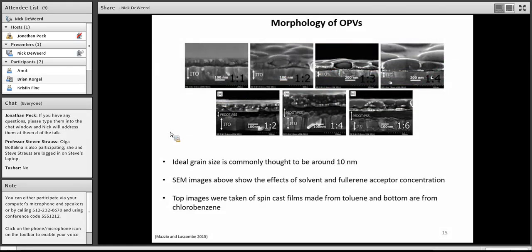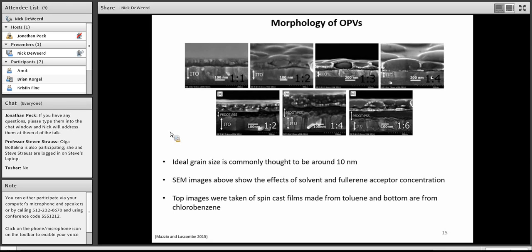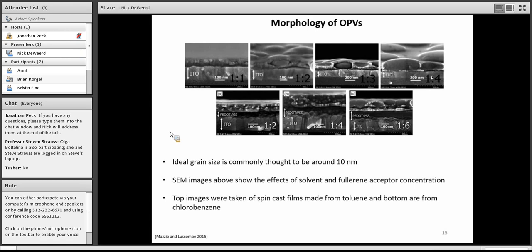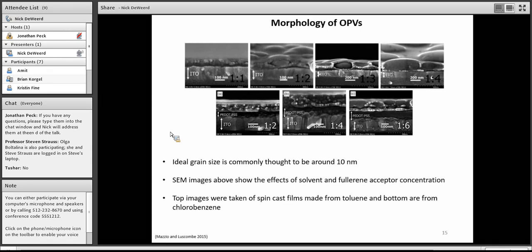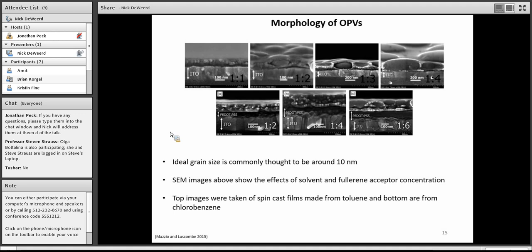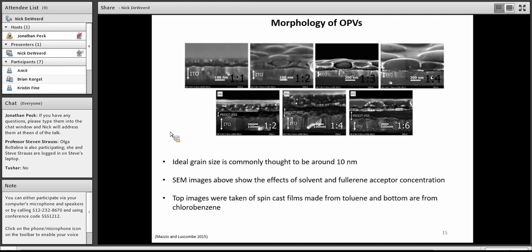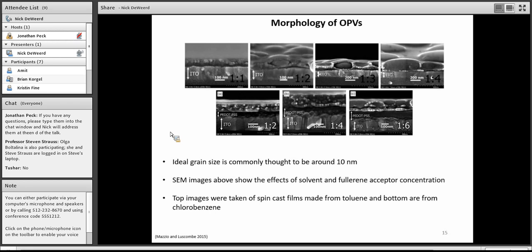That morphology keeps getting more and more complex the more layers you have to deal with. Here is a basic rundown of those morphology problems. This is just a couple of variables being changed, and you can see here how large the difference is in the morphology between different active layers, depending simply on the conditions in which those active layers were deposited. In the top row of SEM images, you can see the ratios actually correlate to the donor fullerene ratio, where the fullerene ratio is increasing, and that's true for the bottom layer as well. The top layer is a spin-coated active layer that was deposited in toluene. As you can see, as the concentration of fullerene increases, we're getting larger and larger aggregates. These aggregates are going to be much larger than the optimal size of the grain size, which is commonly thought to be around 10 nanometers, since that's the exciton diffusion length. And that's been shown pretty reliably, experimentally.